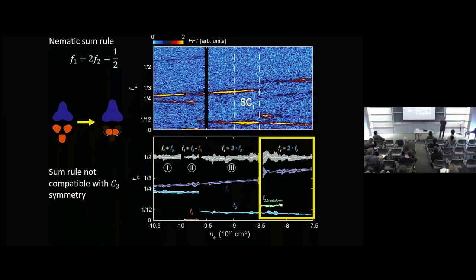Gotcha, thanks. I wanted to ask about that because I think a super interesting question experimentally is, is SC1 associated with a nematic that you just don't see in quantum oscillations for some reason? Because you can break rotational symmetry without changing the sizes of Fermi pockets. That could happen. We just measure the topology of the Fermi surface in some ways, but we can't measure its geometry. So it could be that that's nematic, and nematicity in principle could be everywhere, and maybe that's indeed a unifying feature.